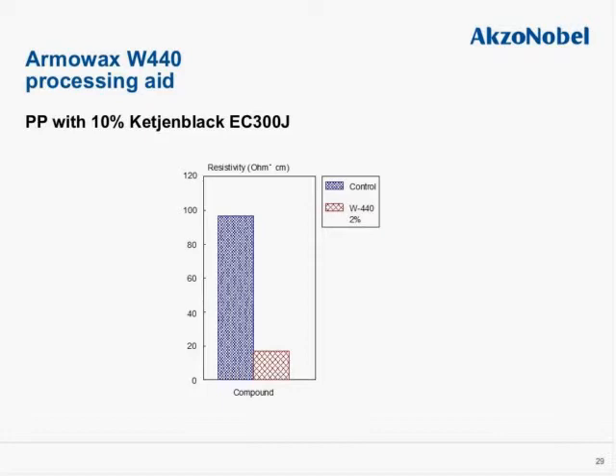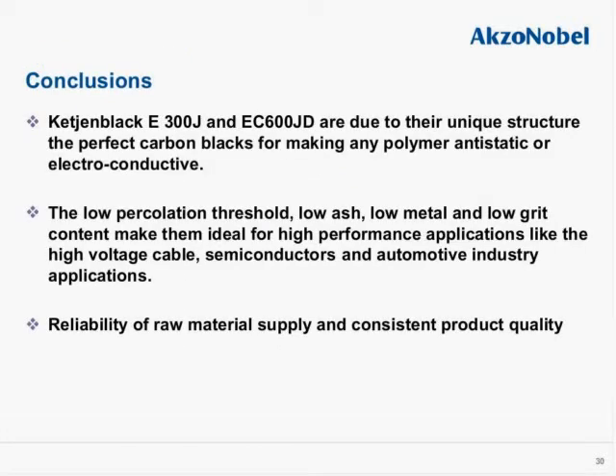We do recommend, we carry Armowax W440, which is a super dispersant, a polymeric ester that is used in conjunction with Ketjenblack. The example that I have here is 10% Ketjenblack EC-300J in polypropylene. Same mixing conditions. The control will have a fairly high resistivity. The other compound that will have about 2% of the processing aid added, the resistivity is much lower, therefore the conductivity goes up. Both polymer matrices were mixed the exact same way. The only difference is that one contains the processing aid, which can assure better dispersibility. But it's not the only dispersant. There are many others that can work with Ketjenblack.